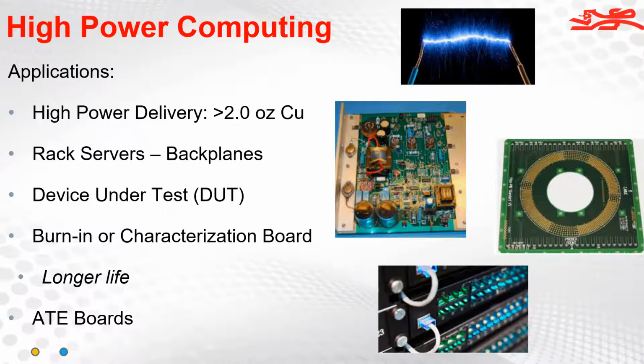Yeah, definitely. One of the areas that we're looking at in particular is chip testing systems, which are commonly used where they cycle the materials up to 90 degrees or 125 degrees. And these boards will have a certain life cycle that they can be operated at. So for example, you'll want to cycle your chips 4 times up to 125 degrees C. After a while, some of those sockets start to degrade and they fail and they can no longer test as many of those chips. And then after a while, those boards become less and less capable and more of the sockets are degraded and they have to take that board out and replace it.